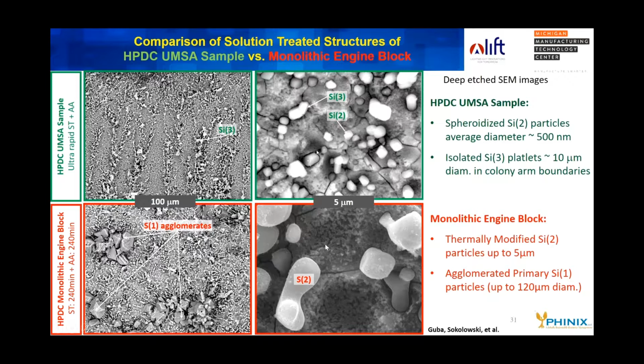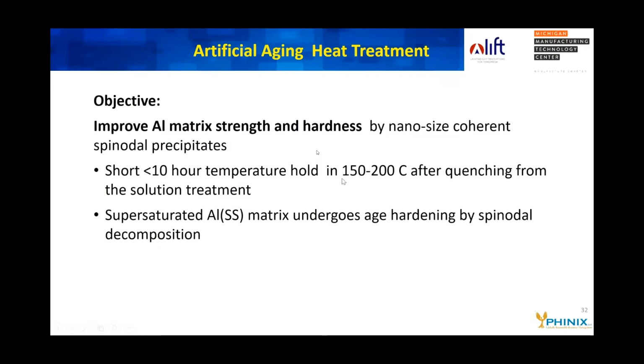Looking at the secondary silicon, long thermal treatment of the engine block partially spheroidized those, but they're around 5 microns, whereas short treatment of our nanocomposites managed to spheroidize the particles without getting them too much above 500 nanometers.